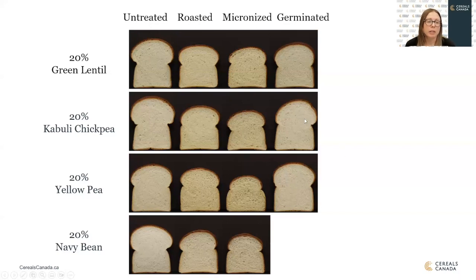You can see that the loaf volume is quite good and comparable to the untreated, and it has a good crumb structure. Our bakers really liked working with these flours. They had really good dough handling properties. However, when we tasted them, they were not good. They had very strong grassy and some bitter flavors come through, which was disappointing.